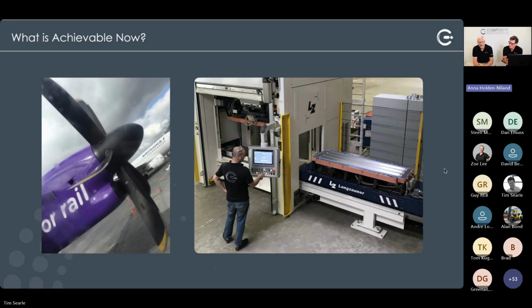The tooling is a multi-impression tool. It makes 4 components at once to really improve productivity. It's heated, it's running around 120 degrees C with snap cure epoxies. And those materials, we run continuous verification of all the materials in the process, including, for example, real-time measurement of the 2K mix ratio, which is so critical.